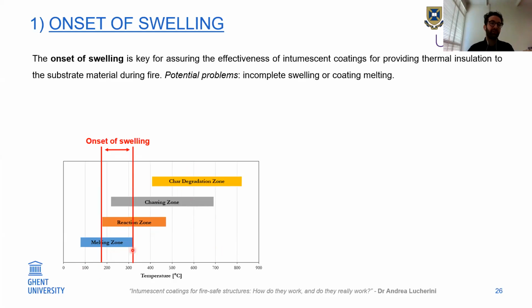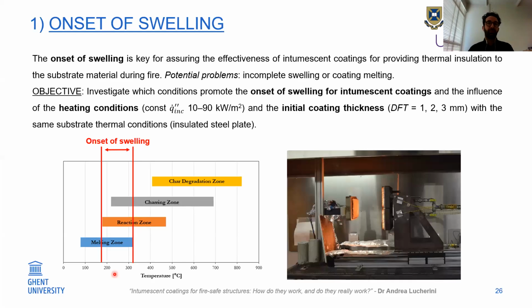And you can see here, from the schema made from the literature review, that it happens in a range of temperatures depending on the different products, different testing apparatus and everything. But the onset of swelling is very important because, as I showed you earlier, there are potential problems, for example incomplete swelling or coating melting that will not allow the coating to swell. So I wanted to investigate which conditions promote the onset of swelling for Intumescent coatings, and how heating conditions would influence it. In this case I used constant incident flux between 10 and 90 kilowatt per square meter and initial coating thickness of 1, 2, and 3 millimeters.